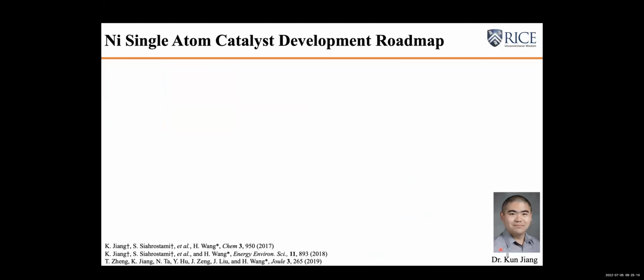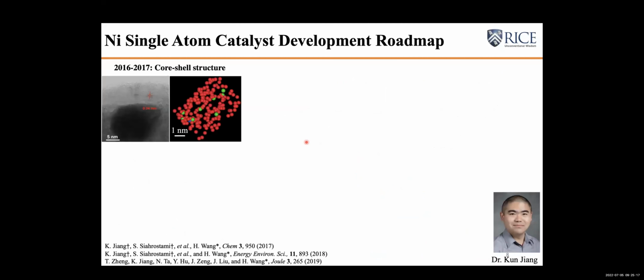So my postdoc at that time, Dr. Kun Jiang, now associate professor at Shanghai Jiao Tong University, started this journey. At the very beginning, we were not that experienced in controlling the synthesis of the atomic site of single atom catalysts. We just mixed a lot of these precursors together and did the thermal annealing. And as a result, we got this core shell structure. So that gave us a very hard time.